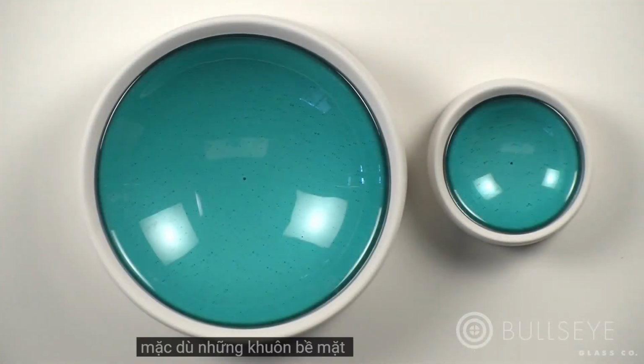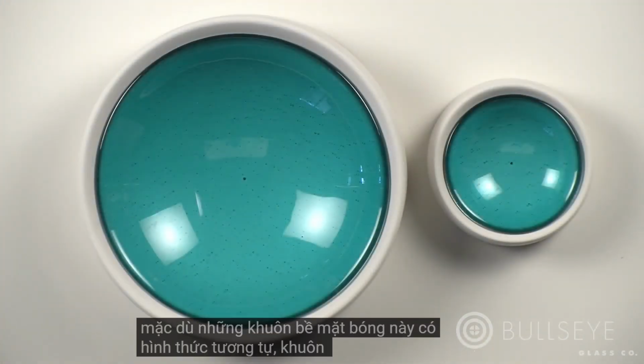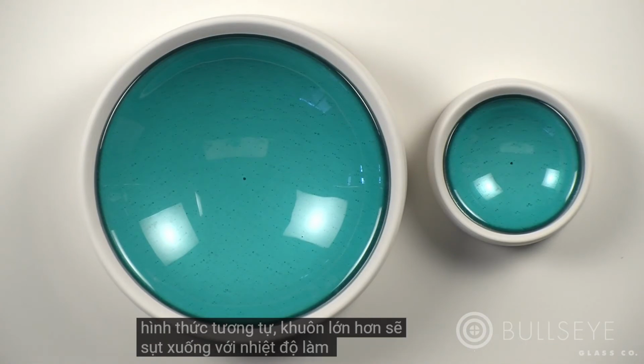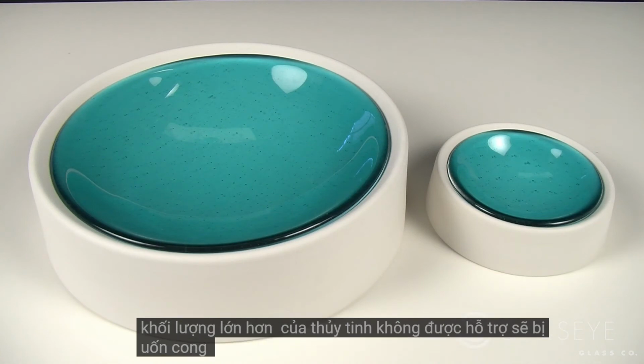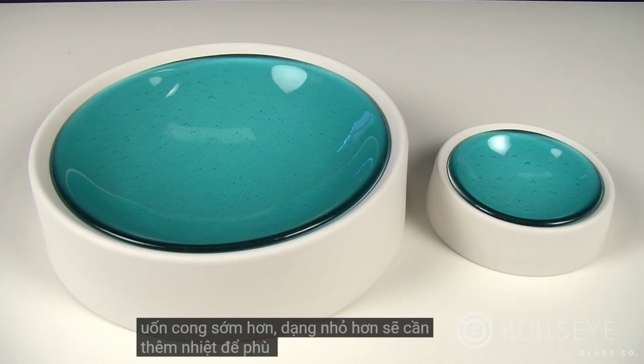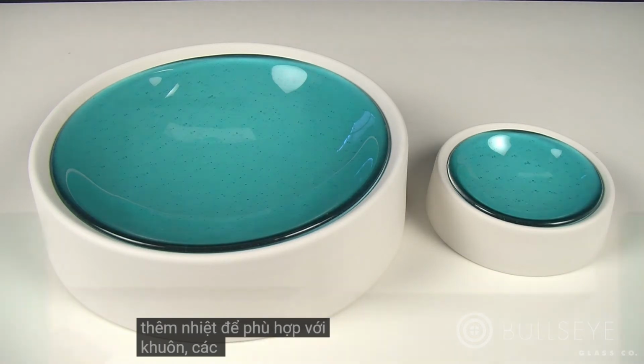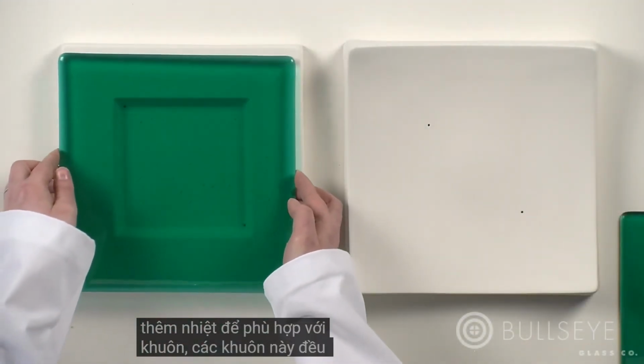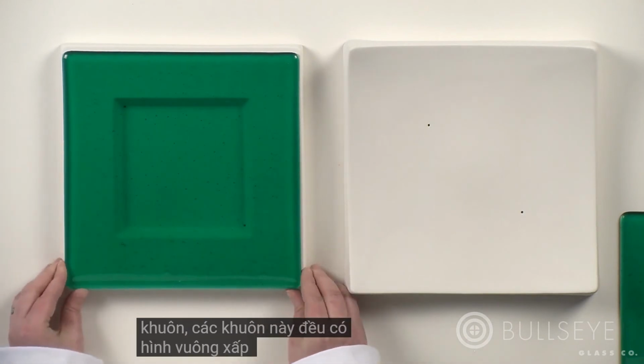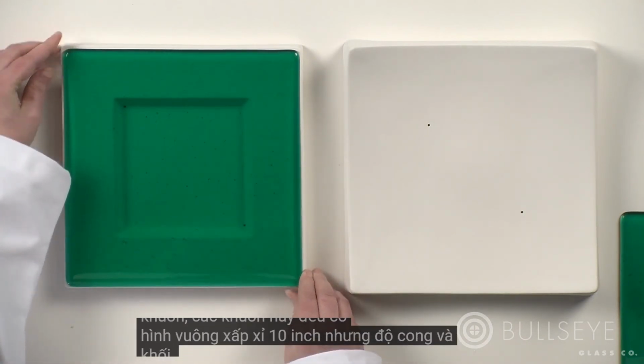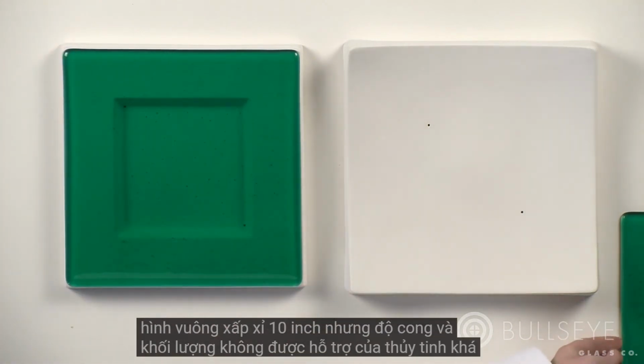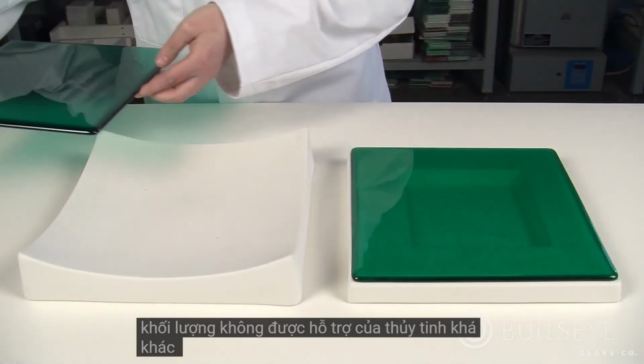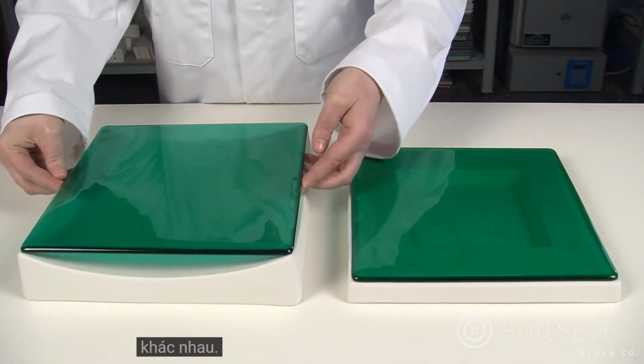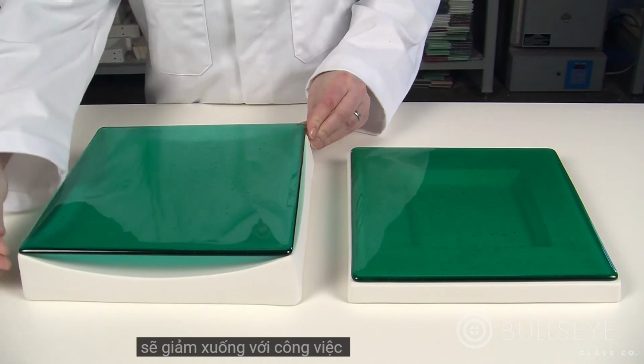Although these bowl surface molds are similar in form, the larger one will slump with less heat work because the greater mass of unsupported glass will bend sooner. The smaller form will need additional heat work to conform to the mold. These molds are both approximately 10 inches square, but the curvatures and unsupported masses of glass are quite different. The square slumper, which supports the glass only by the corners, will slump with much less heat work.